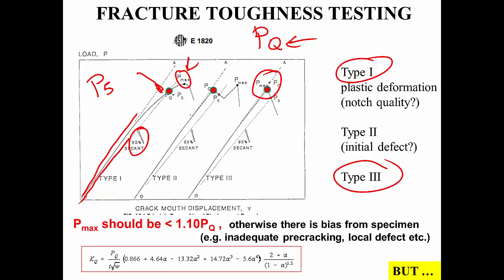The maximum of that curve is essentially the load that we are interested in. The additional complication can occur if there is an initial reduction of the load, but then the load picks up again, and then there is another maximum that is higher than the first one. And in this case, we have the maximum, we have the 5% difference from the slope, this number here, and then we have the initial value. The suggestion from the ASTM standards is to take the initial peak as the failure load under the condition that P maximum is not more than 10% higher than PQ, that first